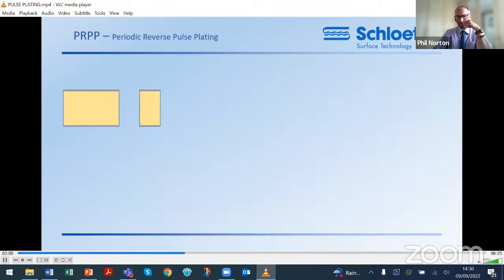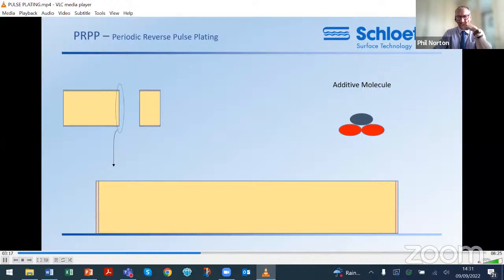In this diagram, representing a drilled hole after direct metallization, we can have a closer look at what happens on an enlarged image of the hole wall. The additive system contains active components which are characterized by having different properties depending on the orientation of the additive molecules. One part of the molecule contains sulfur groups which attract the molecule to the copper substrate, and another opposite part of the molecule contains groups which attract the dissolved copper in the electrolyte towards the molecule.